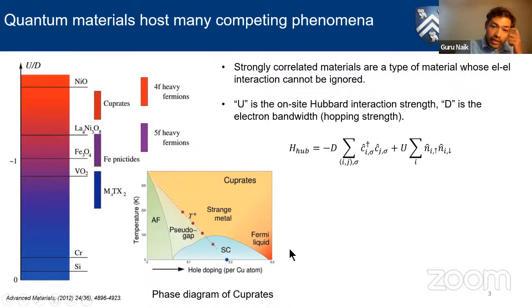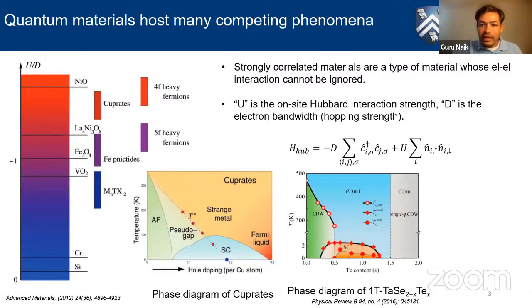Just an example here, a cuprate phase diagram, where we see the semiconducting phase or pseudogap phase, many different ones that we are aware of, antiferromagnetic, etc. Similarly, of course, there is a class of chalcogenides, 2D materials or quasi-2D materials, which also, in fact, exhibit such strong correlations and interesting phase transitions. Here is an example from the 1T tantalum selenide telluride alloy system, which also shows this interesting phase diagram.